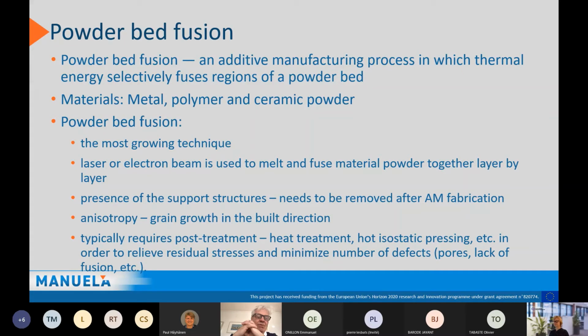From a material point of view, we have what we call anisotropy in metals. That is, we have a certain grain growth, or certain capabilities, so that the properties might be different in the build direction compared to across the build direction. So one has to take that into consideration in some kinds of designs and specs. Typically, we may need some post-treatment, could be heat treatment in some cases, though we try to avoid it, because the more we can go without needing heat treatment, the better.